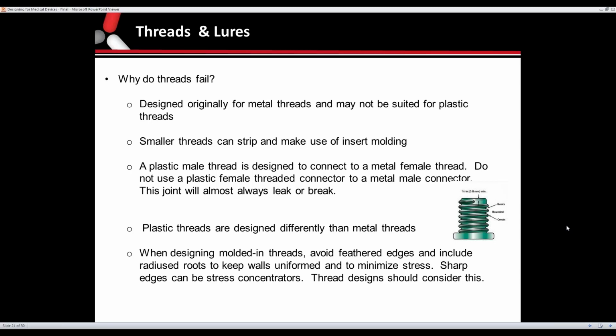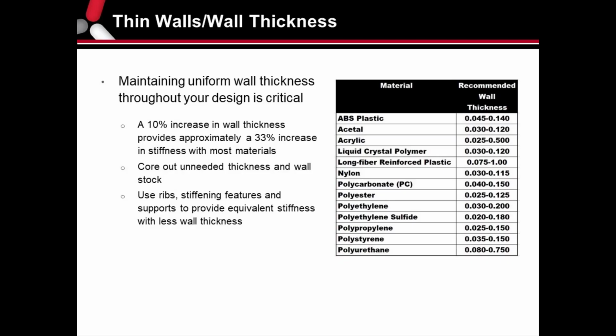Sometimes we have parts that have been designed with 0 lead in, and we find that the threads have been designed and molded properly, but the fit of the 2 parts is difficult to engage unless there's a good lead into that part. And then wall thickness. So we've got a table here on the right, giving some recommended wall thicknesses on some basic materials. The biggest key when designing a plastic part is maintaining uniform wall thickness throughout the part. It's just going to help with material flow, help with even shrinking of the part as it's cooling. Eliminate possibility for sink marks, exactly.